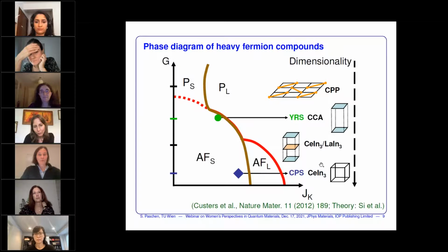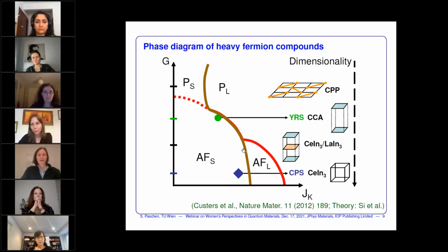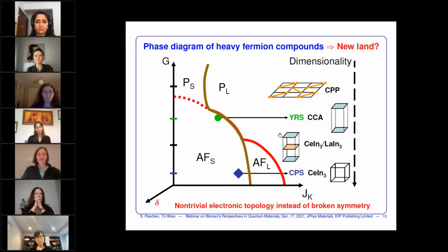So what we then do is grow different materials, study them, and try to create a map. One example of such a map is shown here. It's a zero temperature phase diagram of antiferromagnetic heavy fermion compounds, just as an example, where you see the different phases that exist, and one tries to find out which theoretical parameters govern this whole system and what you have to do to create certain kinds of physics. For instance, along this brown line here, one has very exciting physics associated with strange metal behavior, unconventional superconductivity, and so on.